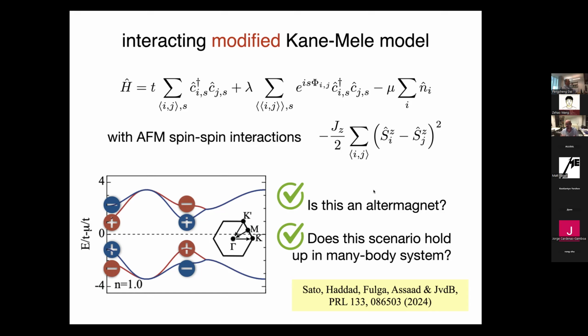Right. And if you break that symmetry, then normally you also allow in the magnetic ordering for Dzyaloshinskii-Moriya kind of couplings, and these DM couplings will in general generate a small ferromagnetic moment, and at the same time the system will have an anomalous Hall effect.